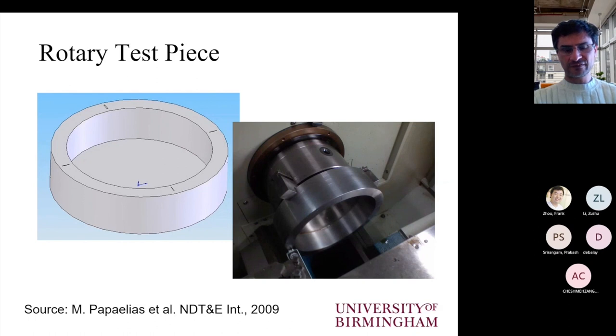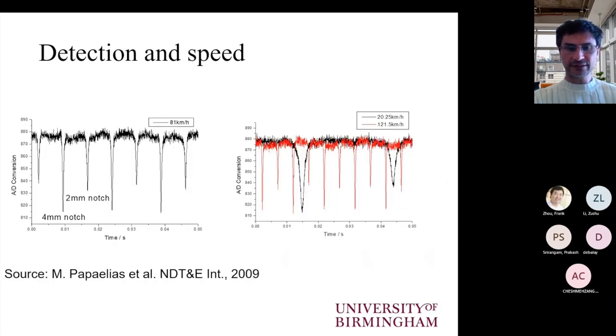So this is the rotary test piece, 4 slots, 2 pairs, 1 pair 2 millimeters deep, the other pair 4 millimeters, that's the turning lathe. And on the bottom left-hand side, you can see the pencil probe that was used for the inspection. Here we did not look at the BZ part of the signal, we only used the probe to assess the depth. So we were looking at just the BX. And here you can see at 81 kilometers an hour and at 121 kilometers an hour, the signal is remaining constant. So we don't have a degradation of the signal despite the changes in the speed.